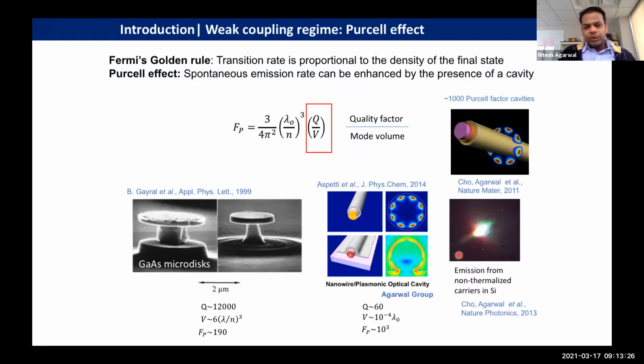So many years back, we started to make these optical cavities by combining semiconductors in different geometries with the intrinsic geometry of the system, or with external plasmonic cavities. And what we found was, if we took a one-dimensional or quasi-one-dimensional nanowire, let's say made of cadmium sulfide, a direct bandgap semiconductor, and engineered a conformal plasmonic cavity, then at certain length scales we could create very strong plasmonic modes along the circumference of the cavity, leading to extremely large Purcell factor enhancements of the order of 1,000. And these enhancements were so large that most of the emission from the excited state came from what we call hot excitons.